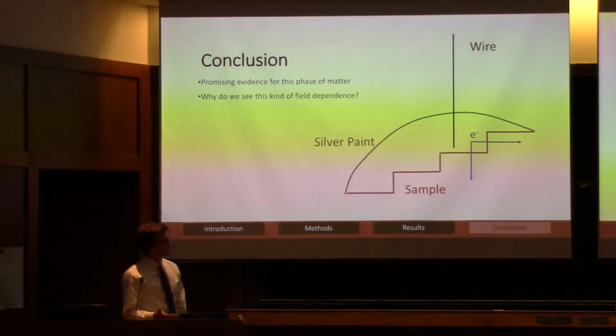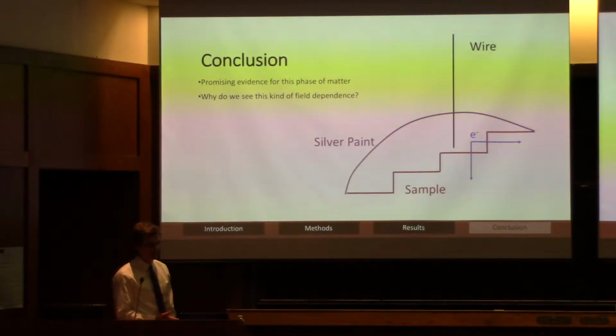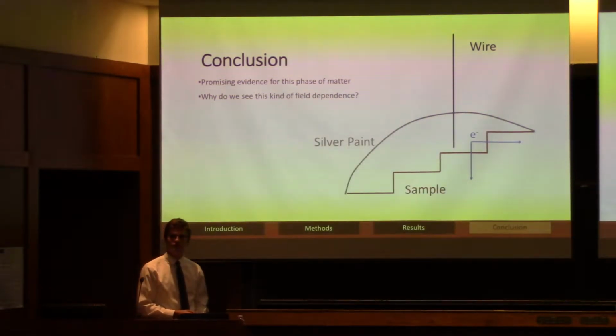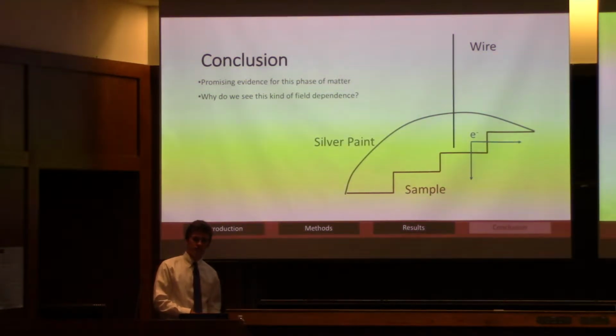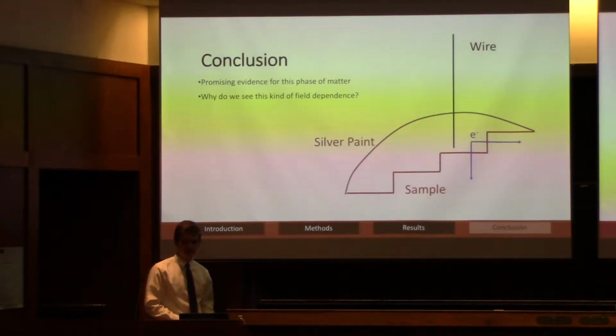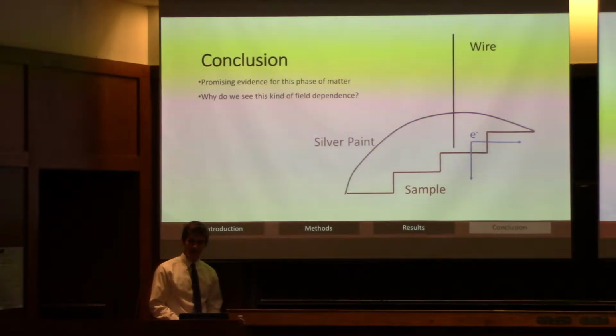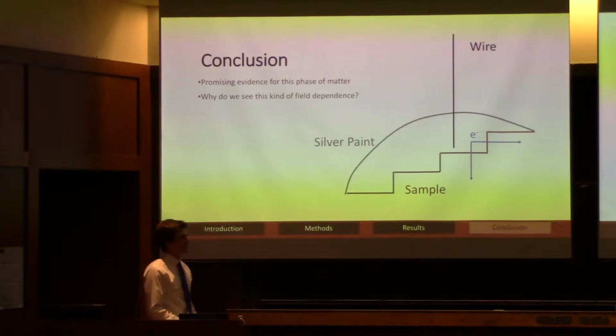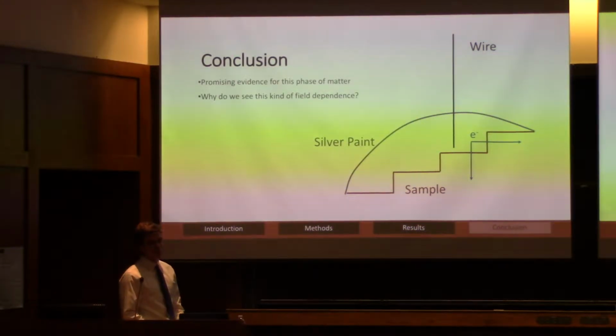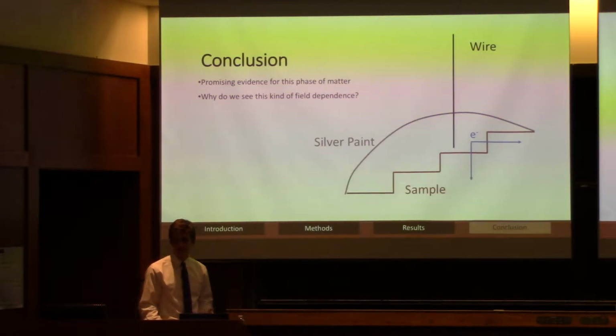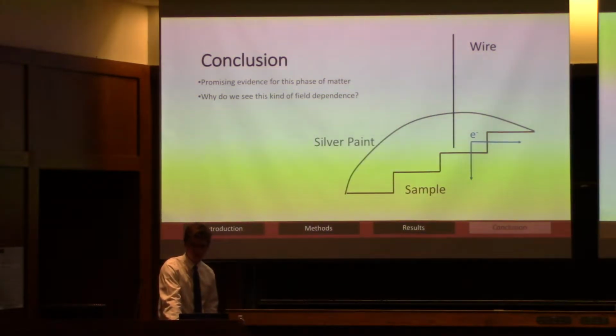This is a very simple diagram of what might be happening. Our sample, when you zoom in close enough, is not perfectly smooth, and when we put that silver paint over it, that silver paint might be covering different layers of the sample, and when we think the electrons are tunneling downwards into our sample, they actually have access to also go sideways. So maybe that's what's happening, and that could account for that strange result we see.